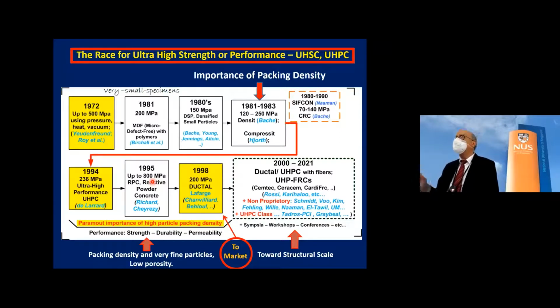Now, again, almost at the same time, Bouygues published a paper saying we got 800 megapascal. However, that 800 megapascal was obtained with added polymers on small specimens, etc. In fact, their equivalent was 200 megapascal. They had several materials, but one of them was 200. It required some heat curing, of course, some specific formulation because it's all secret at this point, but also particle packing was mentioned as being very important, how to do particle packing.